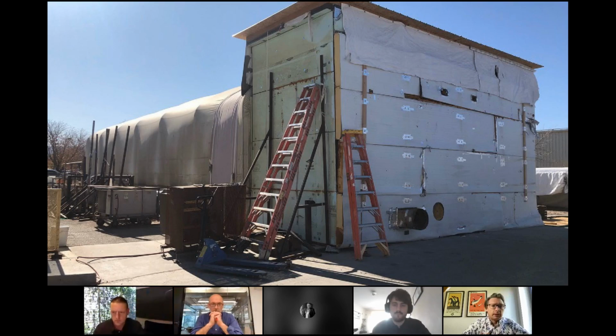I mentioned earlier about the weather. When we're bonding acrylic together, that has to be done in a carefully controlled environment, particularly with regard to temperature. As Sam and Brian mentioned earlier, temperature has a large effect on the size of acrylic, so maintaining temperature during all the fabrication is very important. While Reynolds have internal ovens within their factory, none were capable of fabricating the complete size of the pool. So this specially erected outdoor oven, as we call it, was erected in their yard.